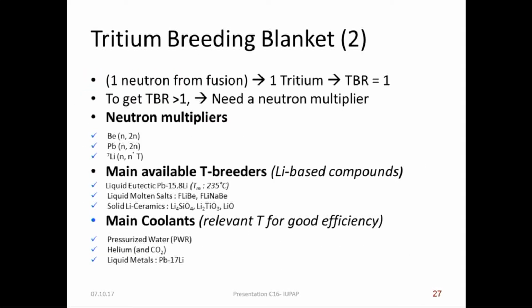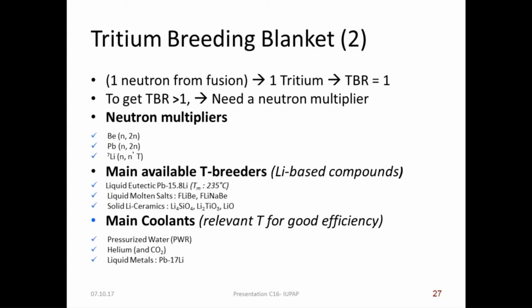So we need a tritium breeding ratio larger than 1, but we have only 1 neutron. So we need a neutron multiplier somewhere, which could be beryllium, lead, or lithium itself. And the main available tritium breeders are not liquid lithium, but some mixture of lithium, which could be a lithium eutectic, lead, and lithium. And the coolants could be pressurized water, helium, or CO2. This is to increase the operating temperature and increase the thermodynamic efficiency in the balance of plant.